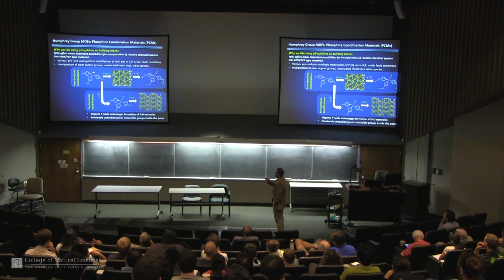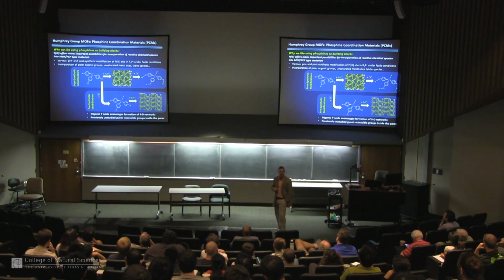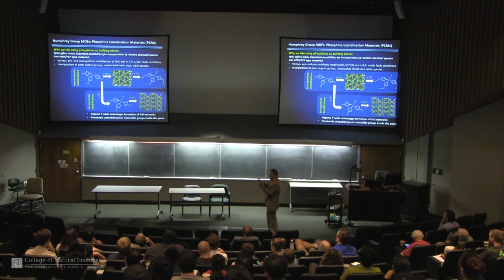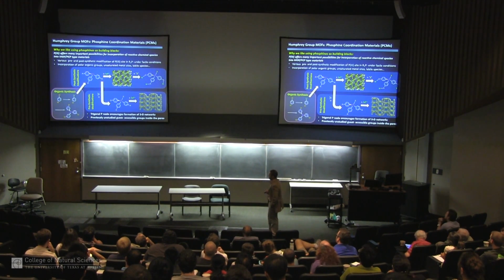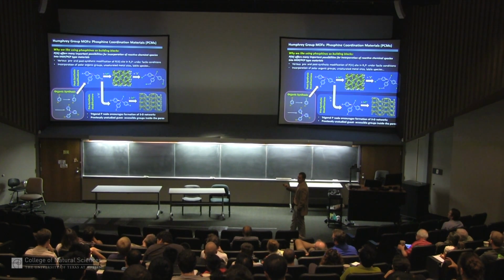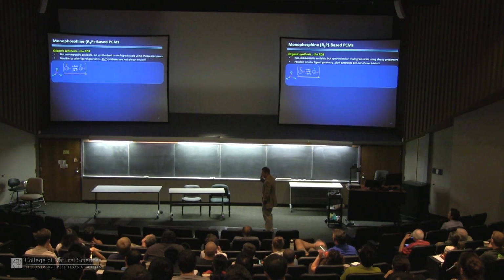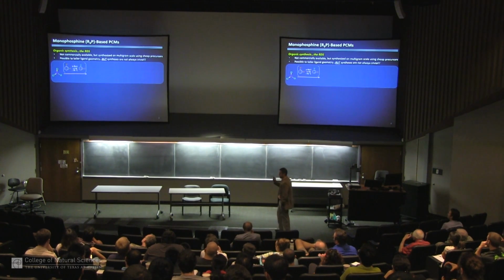All these phosphines, as you can see drawn, are also trigonal, which is great because it means we make porous materials that are three-dimensional and not 2D layered solids. And a lot of people in the MOF field make 9 out of 10 layered materials and just don't publish those 9 out of 10, only publish the porous one. We don't end up with that problem because these are so sterically encumbered that they always make 3D frameworks. And the organic synthesis we do has to be done on a fairly large scale so we can get at grams of material.